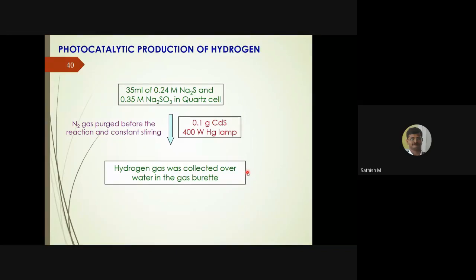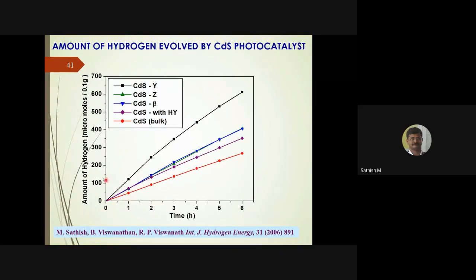So again, we have done some hydrogen evolution. In this case, we use some kind of sacrificial agent: 35 ml of 0.24 mol sodium sulfide and sodium sulfite. So instead of oxygen evolution, this particular reaction will take place so that only hydrogen is liberated. There won't be any sulfur deposition, but still you could see some 600 micromoles of hydrogen produced in 6 hours. That was maybe long before.